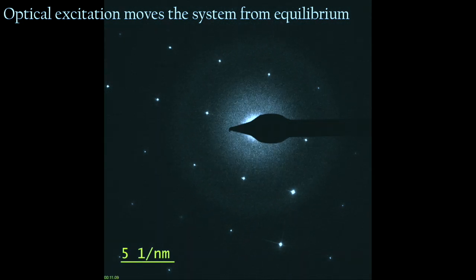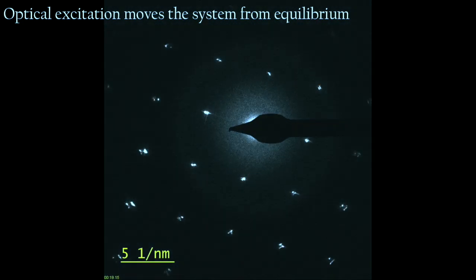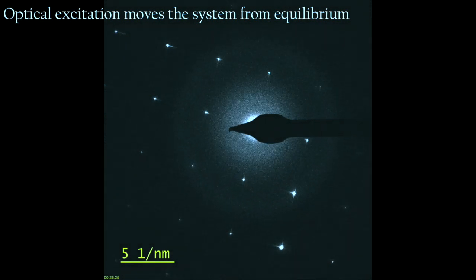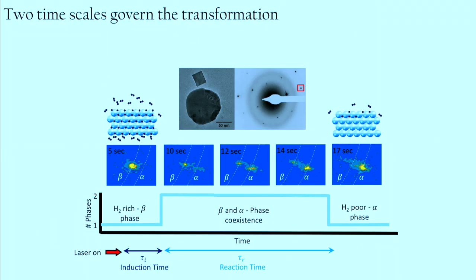So here I'll just play for you a diffraction movie. The light was on at the very beginning, and you can see the diffraction pattern expands, meaning the lattice is contracting, so we're going from the beta phase to the alpha phase. And if we again zoom in to the diffraction patterns, you'll notice that there are actually two different timescales that govern this photocatalytic transformation. We turn the light on.